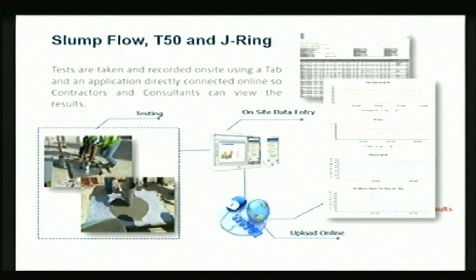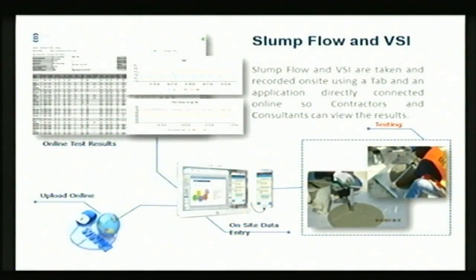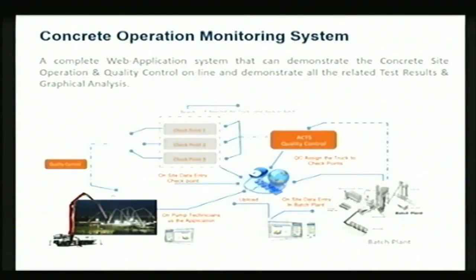So we took slump flow, T50, J-ring, all these SCC tests that you normally do for self-compacting, self-consolidating concrete. We took these tests and we also logged them live. And visual stability index, all this information was uploaded online as we did the test. And again, the monitoring system was important to check the trucks and the flow of the concrete on the pump